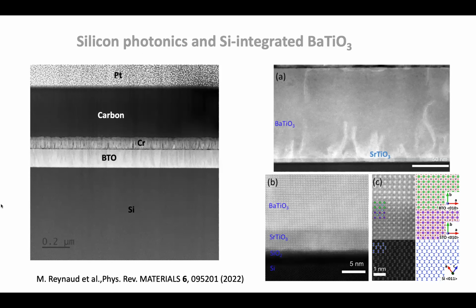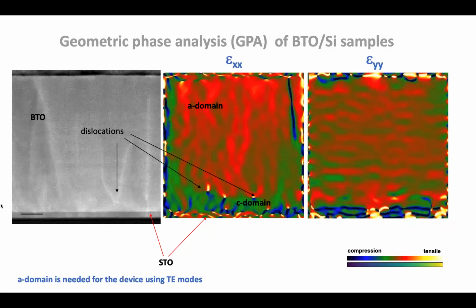And if you zoom in even more, now it looks perfect. But we know there is something wrong with the system because it's not the uniform BaTiO3 I'm finding in the textbook, right? For that, I need to understand the microstructure. I can do microscopy with geometric phase analysis and look at the strain maps, and I see that my film is actually c-oriented, meaning polarization is out of plane due to compressive strain. I use an STO buffer to put it on silicon.